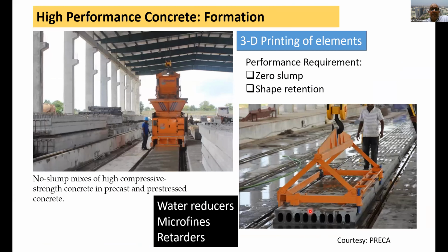The other place where we use these very stiff concrete mixes is in the production of these hollow core slabs, which are used extensively in precast construction. This again is possible by using very stiff concrete mixes. So these are literally produced by an extrusion process. You extrude concrete, and after it is extruded, it will have the shape, and the concrete is expected to keep these holes, keep the shape without collapsing. And that's only possible if I can engineer the material by using these water reducers, microfines, and retarders, which are all admixtures that we use, controlling the rheology of the material to deliver the stiff performance.